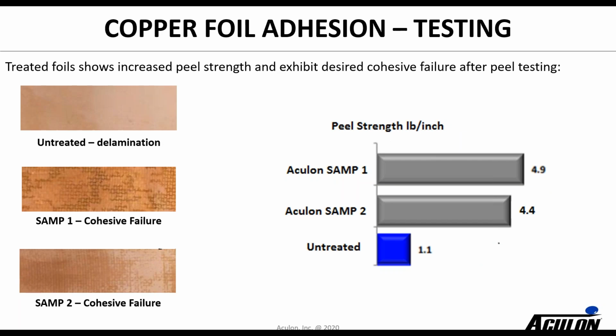Here's a slide that shows the peel strength results, and not only are you seeing the peel strength increase, but we're changing the mode of failure, which, in the adhesive world, is always an important question: where is the failure occurring? Whenever you can shift the failure from the interface into the bulk, where you're getting cohesive failure, then your primer is really doing a good job. So you're just at that point limited in strength by the actual adhesive, not the interface.